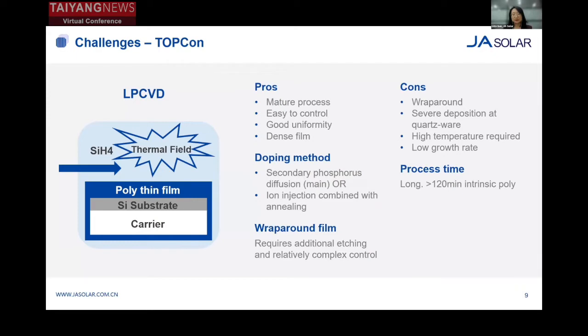The wraparound film can result in the decrease in the optical and electrical performance of the cells, such as open circuit voltage, short circuit current density, and fill factor. And it requires extra cost and equipment to remove this wraparound film. In addition, due to severe deposition at the boat, the boat needs to be replaced frequently, and this brings up the production cost. Another challenge is to reduce the process time. Now it requires more than 2 hours to deposit the intrinsic polysilicon film.